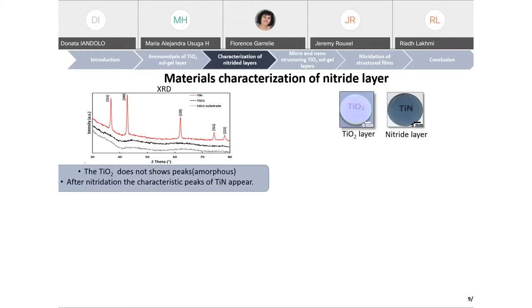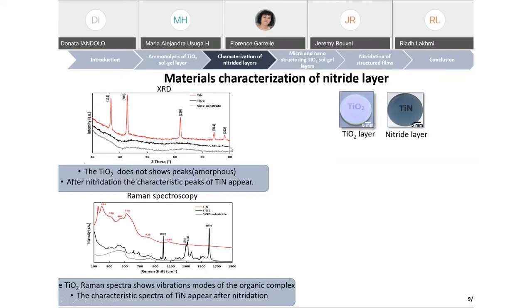For the X-ray diffraction, the titanium dioxide does not show peaks. This means that the titanium dioxide is amorphous. When we do the nitridation process, we can see that the characteristic peaks of titanium nitride appear. Using the Raman spectroscopy technique, we can see that the titanium dioxide Raman spectra show some vibration modes of the organic complex, titanium isopropoxide benzoyl acetone. When we realize the nitridation process, the characteristic spectra of titanium nitride appear after nitridation.